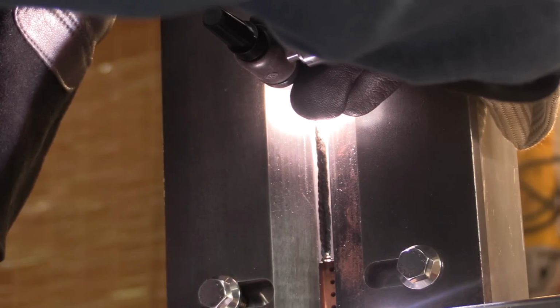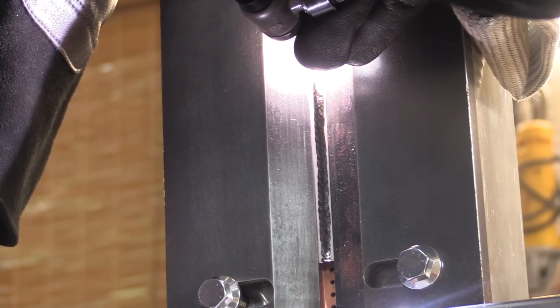I finally settled into a groove here where I'm feeding the rod almost right into that arc and it's not sticking at all with me. That's what I really want to do, but a little out of practice on this. I'm using a 0.045 diameter filler here, but actually I'd prefer one size bigger, a 1/16, just for the rigidity so it won't flop around and stick with me, so I can stab it right there in the hot part of the puddle. But I'm getting used to it.